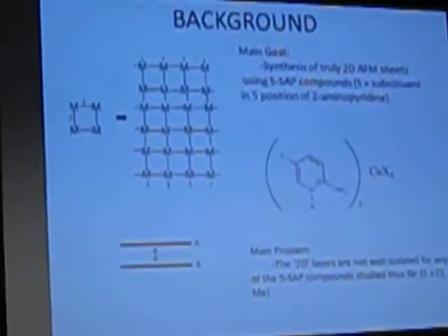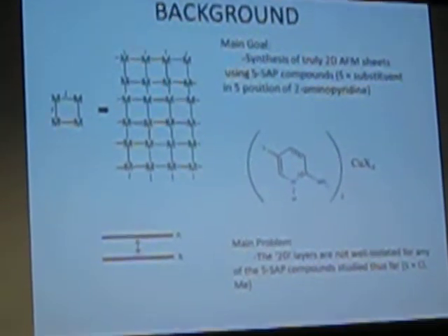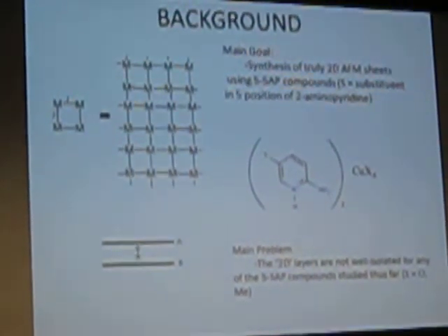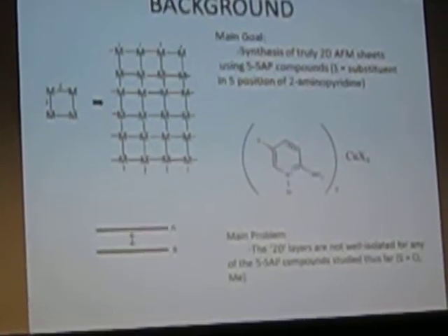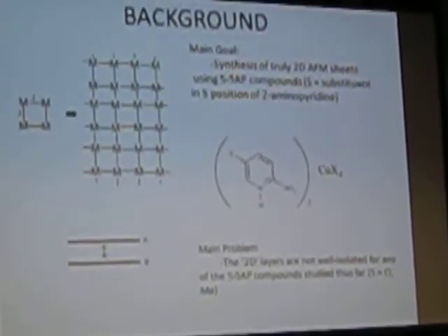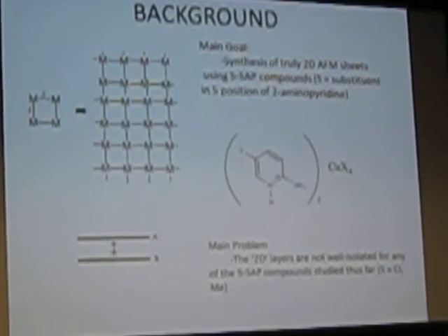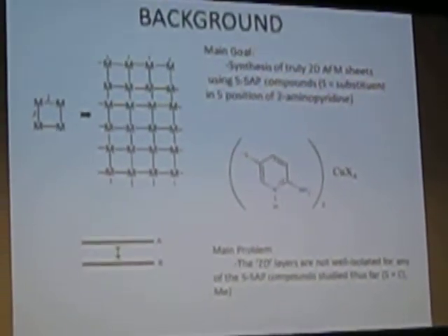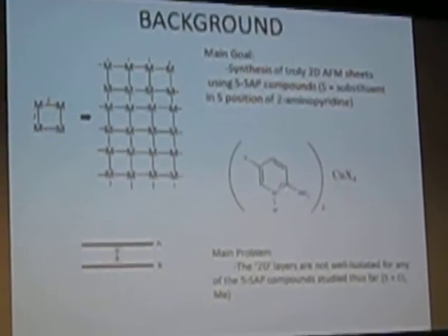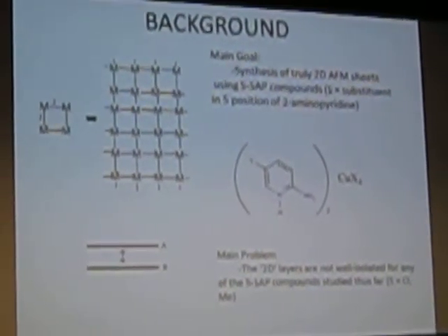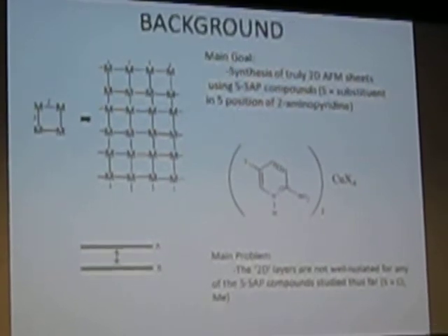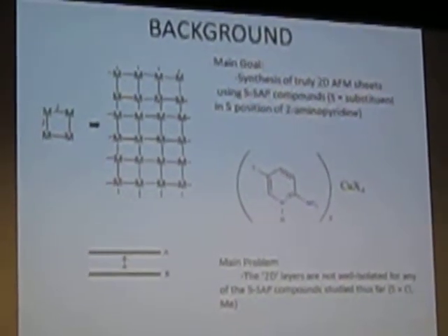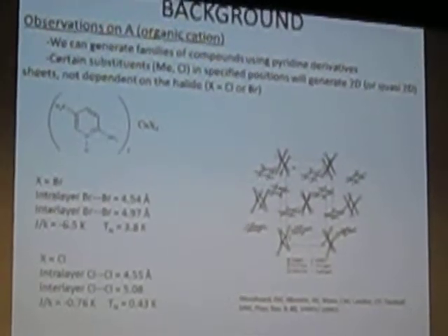So a little bit more on how we're actually designing these materials. We've developed a family of compounds known as 5-SAP compounds, where S is any substituent in the 5 position of 2-amino-pyridinium, the cation. And the substituents that have successfully created these 2D layers are the chloride and the methyl. I'll be focusing on the methyl group. The main problem with these materials is the inter-layer distances are too close to constitute a truly 2D material.